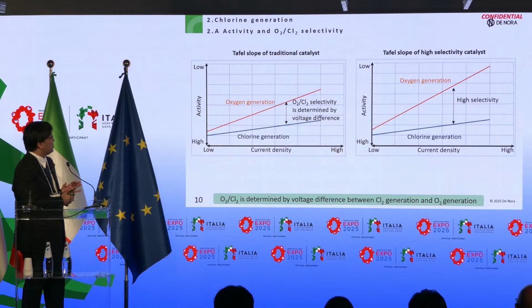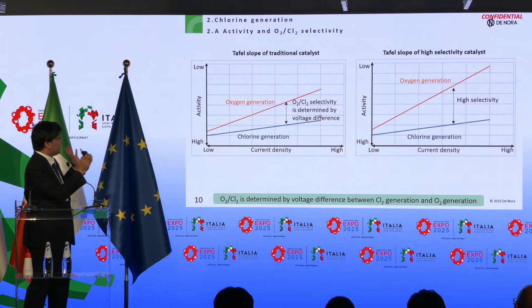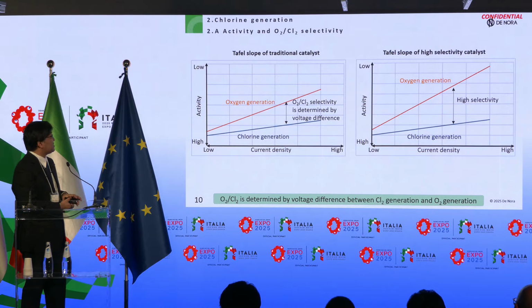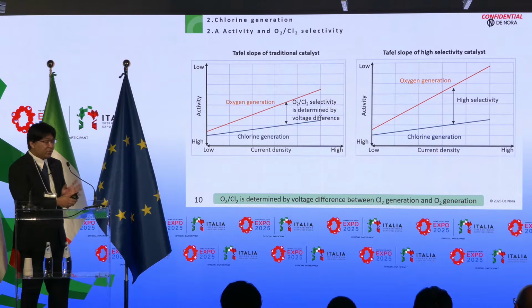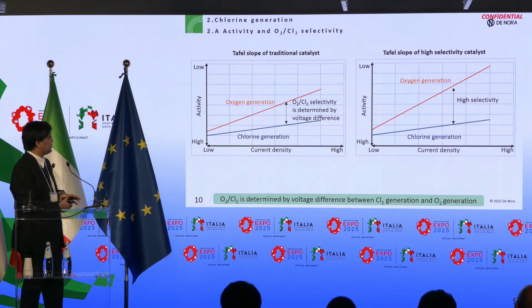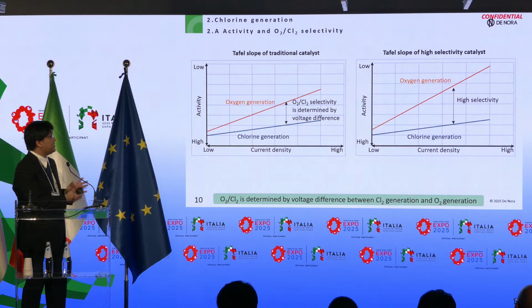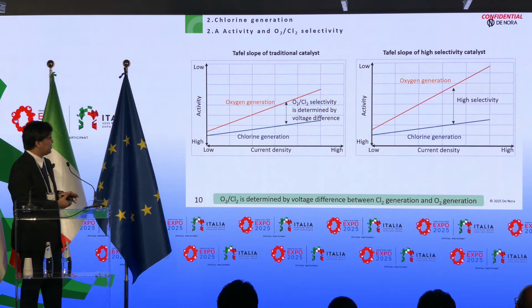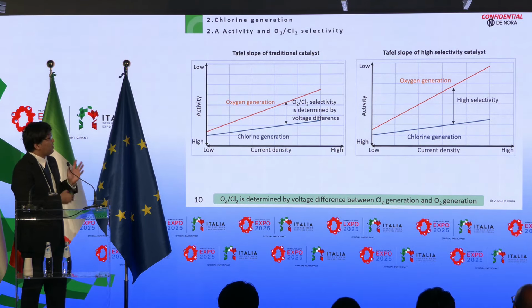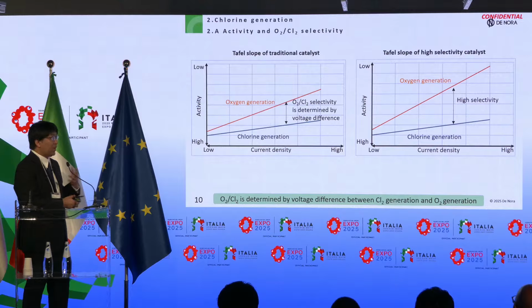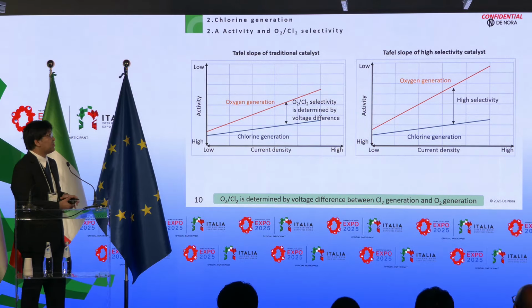Chlorine and oxygen selectivity is determined by the voltage difference of chlorine generation and oxygen generation. Basically, the oxygen generation Tafel slope is much higher than chlorine generation. So at the current density in industrial use, chlorine generation is dominant. And we can control the chlorine selectivity by changing the catalyst, bulk metal, and preparation conditions.